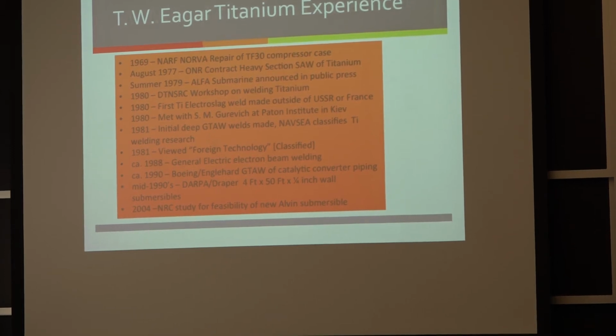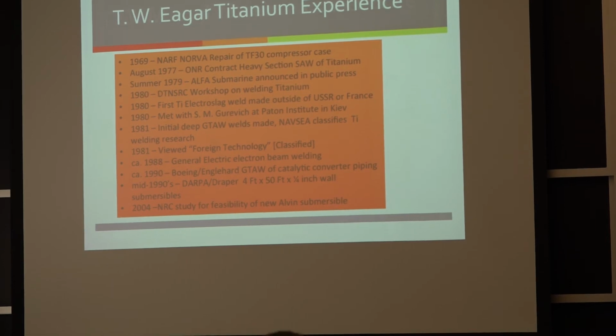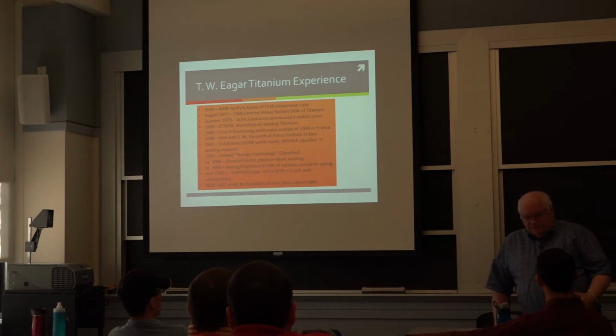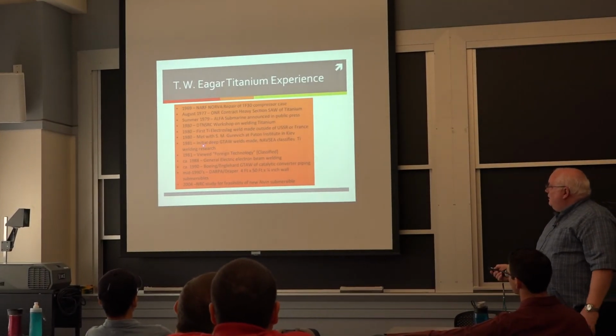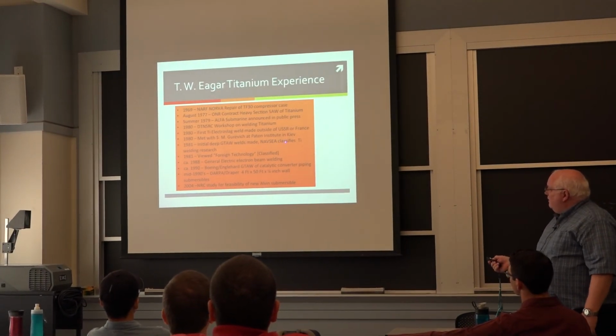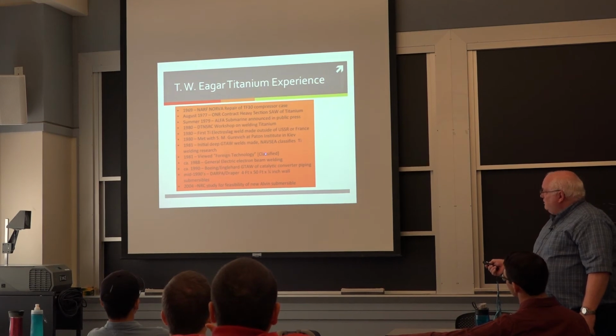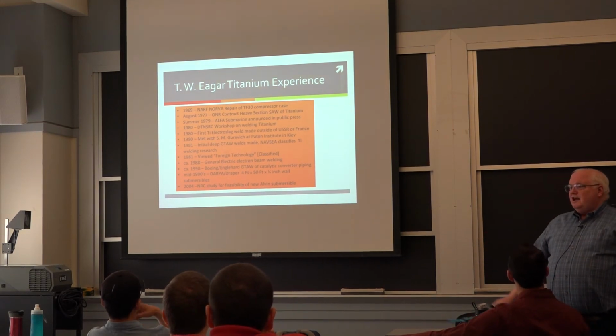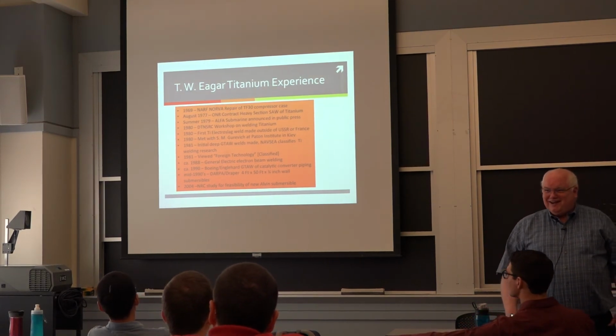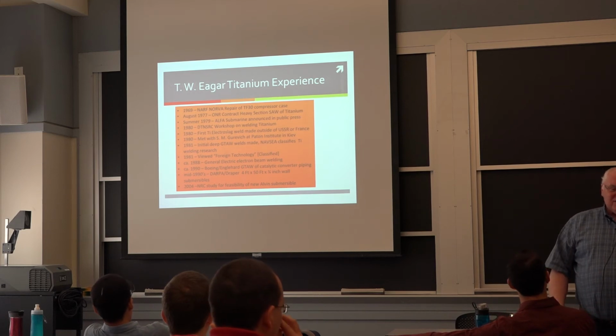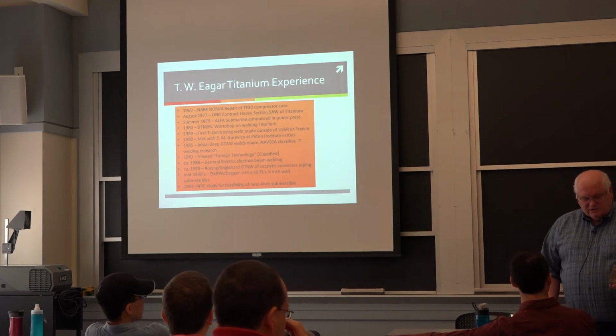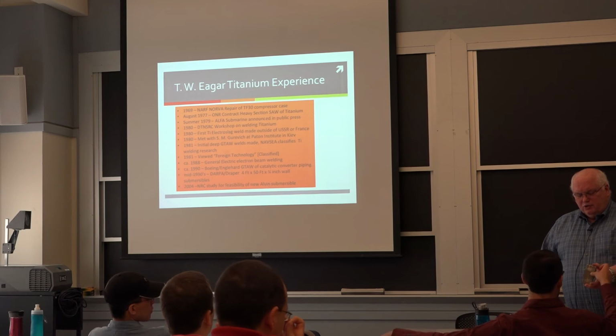And so I knew that submerged arc welding, while we might be able to make it work, was going to be an economic disaster. I made the Electro Slag weld, reported it to the Navy, and then what did they do? Well, in '81, they classified all titanium welding research. So I was out of titanium welding for a while, okay? Because you can't do classified research on campus. This weld that I passed around yesterday is a 2-inch Electro Slag weld.